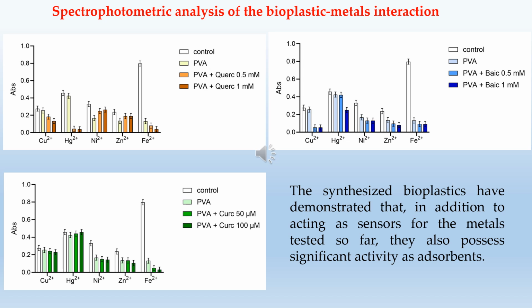This interaction causes a variation in the absorbance values at 620 nanometers that is evident already after 4 hours of incubation for all the flavonoids tested. From the experiments carried out in the presence of metal ions, it was evident that the synthesized bioplastics, in addition to acting as sensors for the metals tested so far, also possess significant activity as adsorbents.